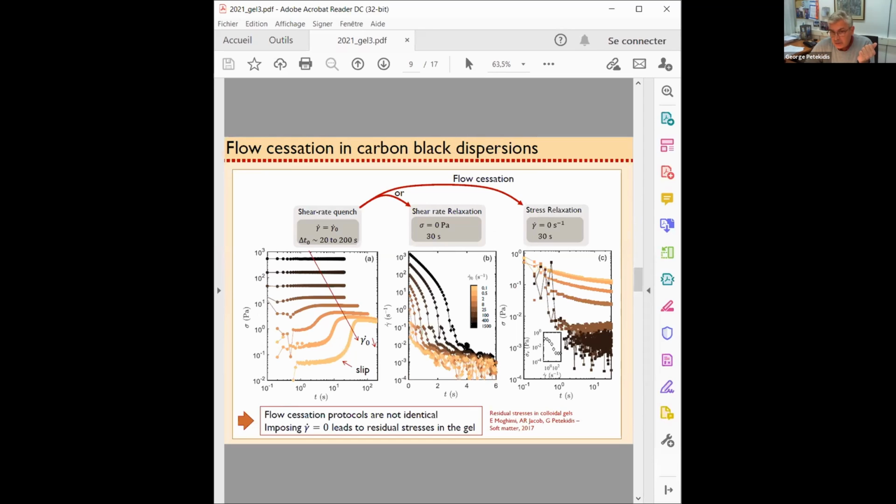I don't think it affects your results in terms of making stronger or weaker gels, but I think these curves are quite tricky to understand, simply because at high rates you have the inertia of the tool. So one might consider just doing a very sudden stop, rate 0, maybe for half a second, and then put stress 0. So that is more a comment. I don't know whether you've done it or thought of it.